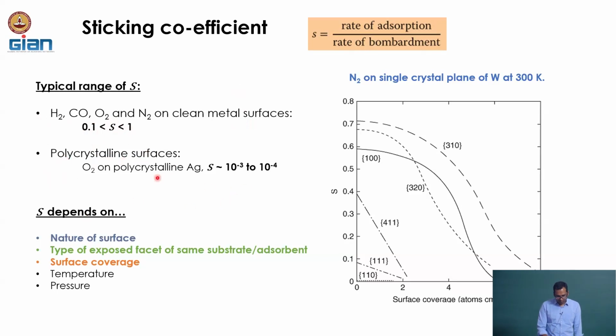For example, if I have a polycrystalline surface, and here is an example of a polycrystalline silver surface, and I am trying to adsorb oxygen on it, the sticking probability is now between 10 to the power minus 3 to 10 to the power minus 4, which is really low, and these are going to affect how my reaction is happening. So the sticking probability depends on the nature of the surface, the type of the exposed facet of the same substrate or the adsorbent, the surface coverage, that means how much of the adsorbate was already present on the surface, the temperature and the pressure as well.